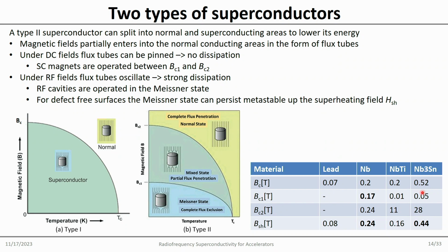A material which could be interesting for both wires and cavities. Actually, both are used already for wires. For example, the LHC, the inner focusing system where you need very strong field just close to the detector, is where we can go higher. There's a fourth line here, as we call the superheating field. So superheating field is how long this flux-free state could persist for a perfect surface.